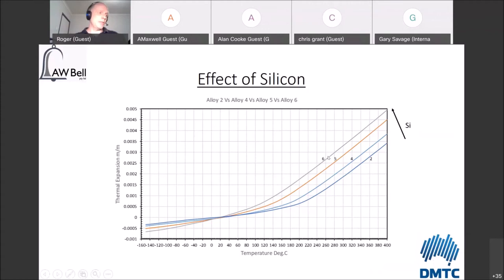Now, silicon does improve fluidity of the metal, but it doesn't help at all in terms of the thermal expansion coefficient. It also, as I was alluding to before, doesn't help in terms of the hot tearing either. So keeping silicon very, very low is certainly advantageous.